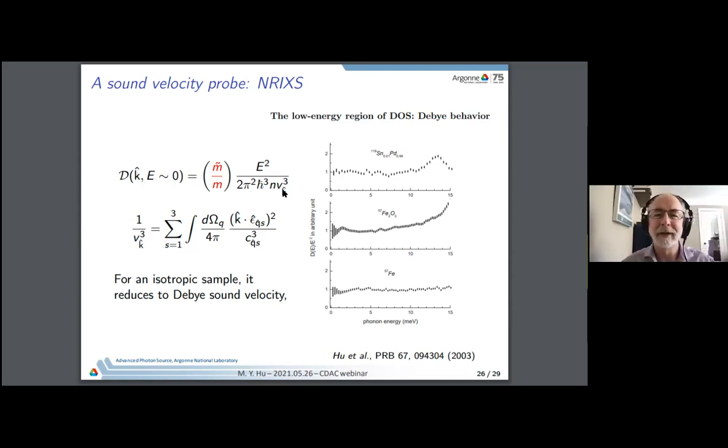I can also comment on what Wenli just asked. If you have another technique, such as neutron scattering, you have the same problem where the different isotopes have different scattering weights. But if it's an iron alloy with something else, a binary alloy, you can sort out the two partial densities of states for the iron and the other element by comparing the neutron data to the iron-57 nuclear resonance scattering. But you have to have the same resolution for these two, so there's another issue with that. But anyway, you were quite right about the long wavelength limit, Michael.